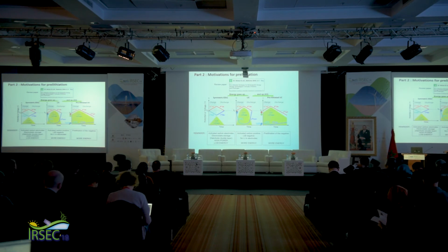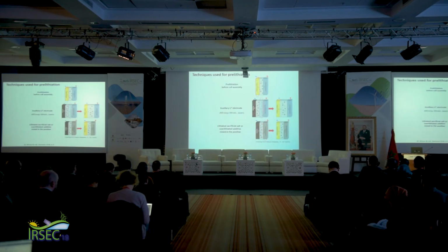And the two electrodes of these systems are fabricated with no lithium content initially. So in fact, to increase the performance, you need to pre-lithiate the negative electrode to provide lithium in the structure of the negative electrode and to build the SEI layer. And in this case, you can obtain more energy, but also better power and longer durability. Okay, so this is a short summary.